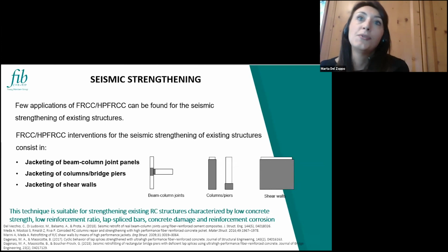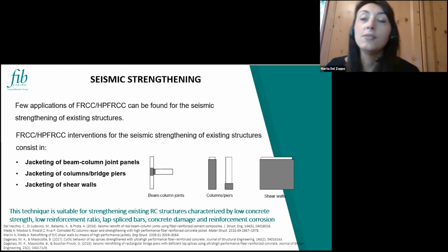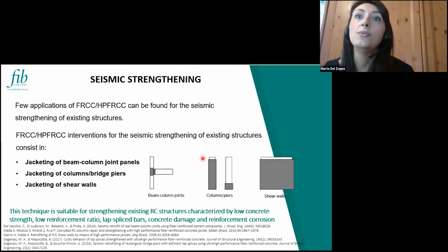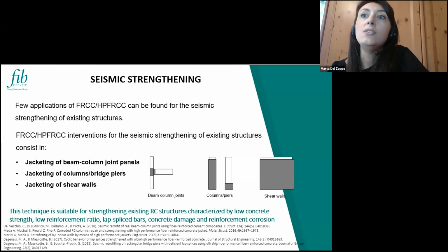So FRCC and high-performance FRCC can be adopted as a seismic strengthening solution in terms of jacketing for the beam-column joints. So we can apply an overlay of this FRCC or high-performance FRCC on the joint panel to increase the shear capacity of the joint. Or in the form of jacketing for columns and shear walls. And this jacketing can involve the full length of the specimen or just be localized at the bottom, for example, in the case we are dealing with the plastic hinge region or the lap splice region. But in general, we can say that this kind of strengthening solution is suitable for structures that are characterized by very low quality concrete and also some deficiencies like low reinforcement ratio, lap spliced bars, and also in the case of deterioration, so when we have other problems related to the corrosion of the members.